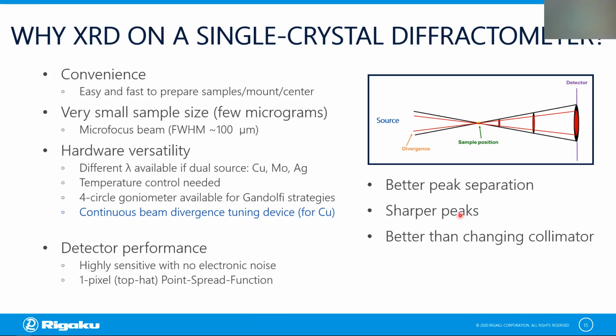Sharper peaks, your peaks will have a smaller full width at half maximum, and it is better than just changing the collimator, because when you change the collimator, you have no control of the size of the pinhole at the tip of the collimator. So most likely you take too much of a hit in terms of intensity, whereas with that divergence slit, you can actually move it slightly into the beam, just what you need to resolve your reflections or your powder peaks, and therefore you take much less of a hit in terms of intensity.